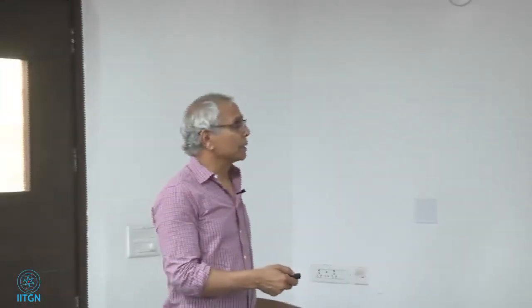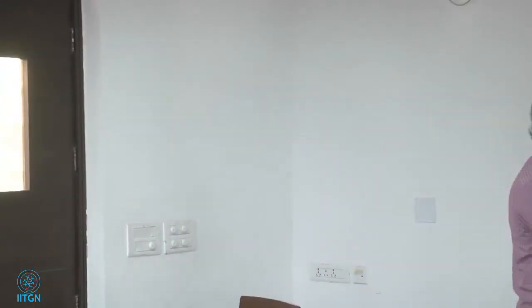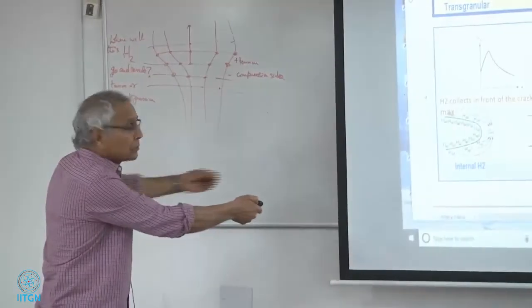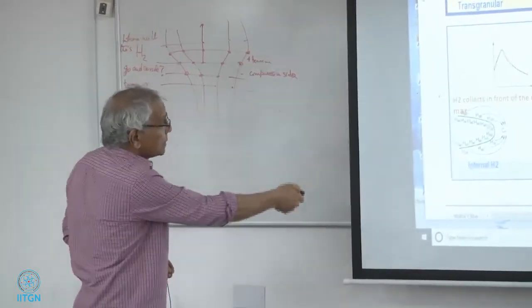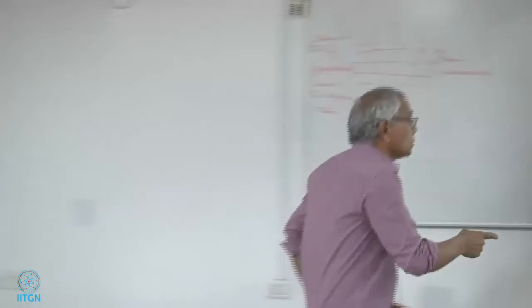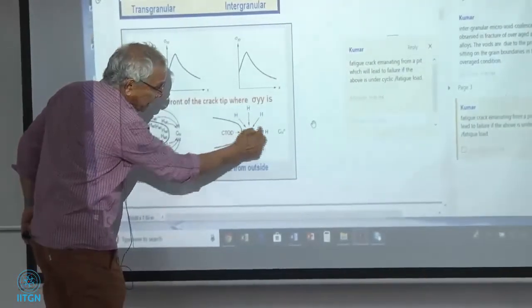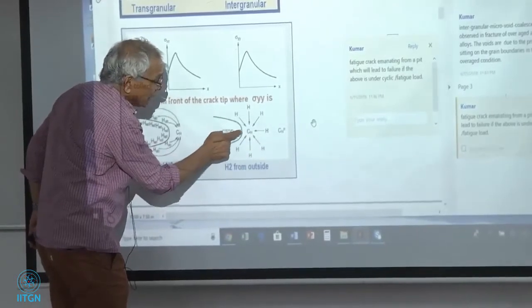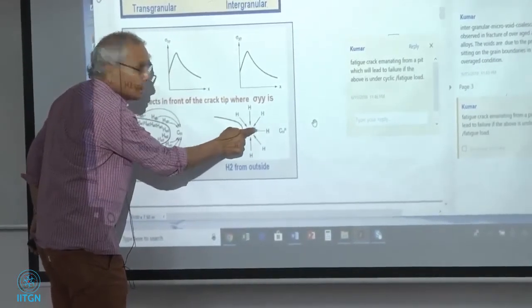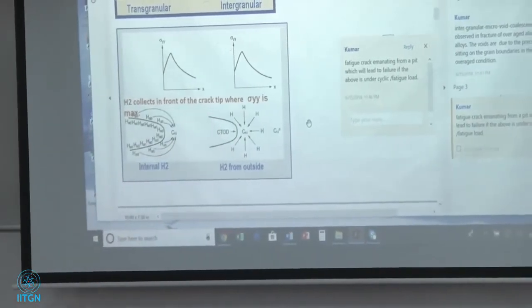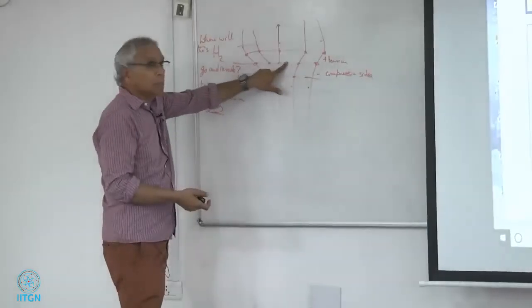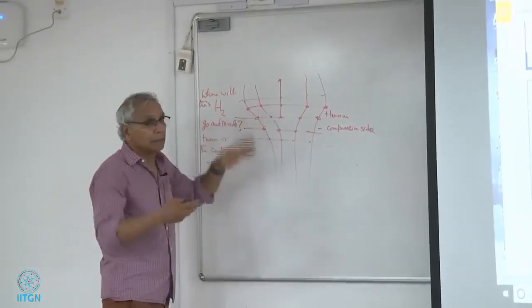Okay, there's so much material out there, right? And same thing, even if it's hydrogen coming from the outside, the crack tip will attract the hydrogen from the outside. It will all collect there, again increasing the concentration. Because now these bonds, all this lattice structure here, is going to experience the stress field from this crack tip, and this hydrogen is sitting somewhere, and it will reduce the energy. It can reduce the cohesive energy. This bond may break, this may break, that may break. So you can have hydrogen embrittlement. Right? Makes sense?